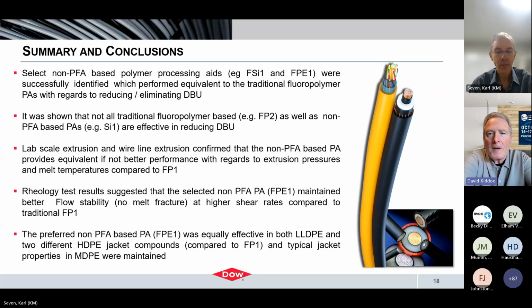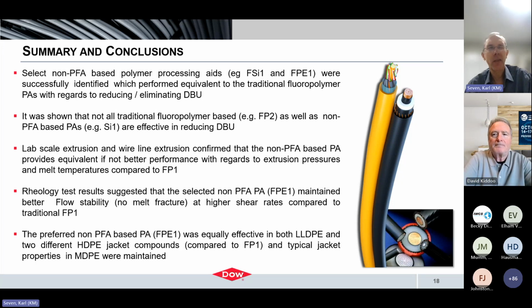Fair enough. Are the melt temperatures of the polyethylene jackets changed at all by using different polymer processing aids? For example, does the polyethylene jacket melt at a higher or lower temperature based on the processing aid? Well, within the scope of the study I'm presenting, I did not see significant shifts in melt temperatures. And of course, we also looked at melt temperatures within wire extrusion processes, and I didn't see large shifts in that regard.